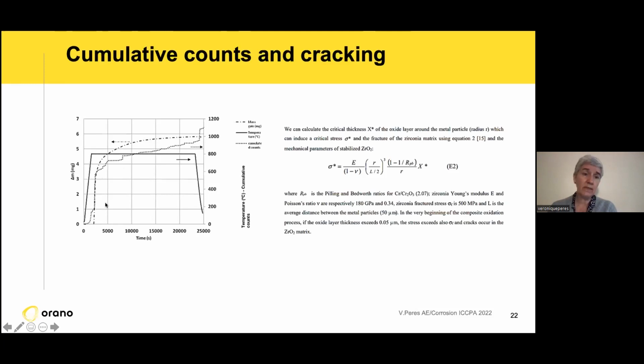And in this case, not like the two previous ones, you can see that since the beginning of the experiment we have noise. That means the cracks are formed at the beginning. The cracks and the noise are due to the constraints of the layer we form around the precipitate, and we calculated the thickness of this layer, to see whether it means some constraint that can provoke cracks in the sample.